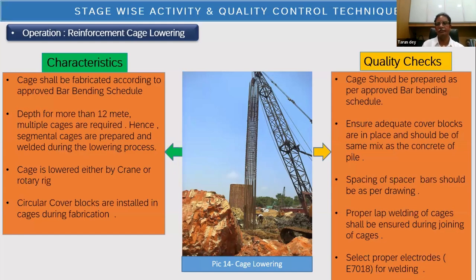Now, while you do this activity, your checkpoints could be: the cage is fabricated as per the drawing or as per the bar bending schedule you have made. The number of bars is the same as per drawing, links are the same as per drawing. Then the joints are properly welded so that they take the load. Spacing of cover blocks should be adequate. Proper lapping should be maintained as directed or as specified. Do the welding preferably with E7018.